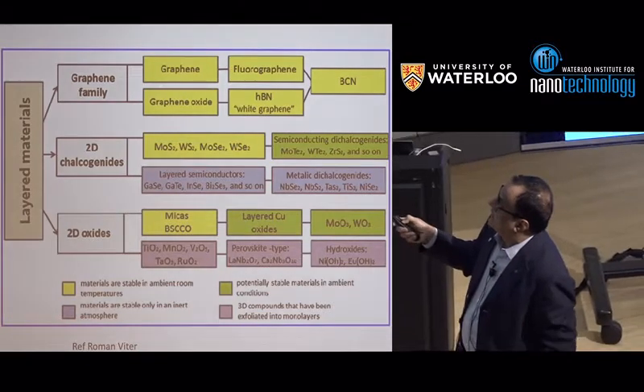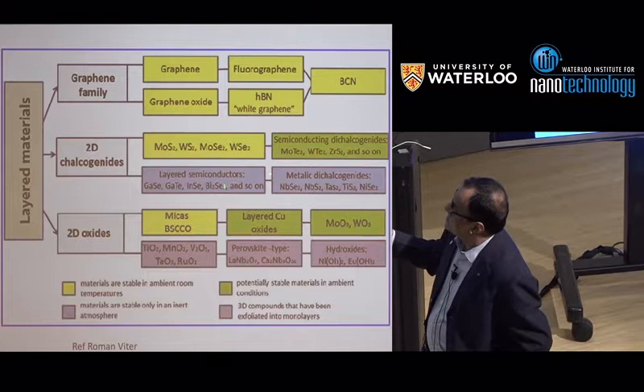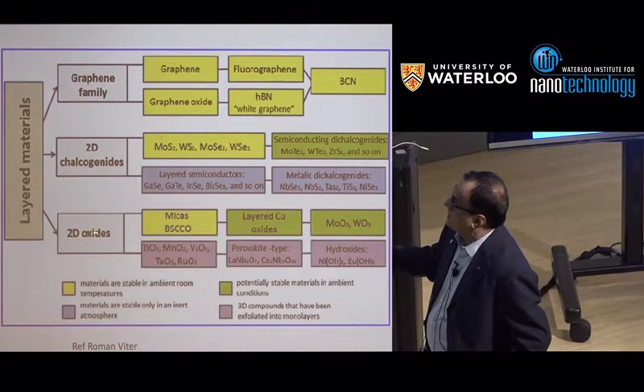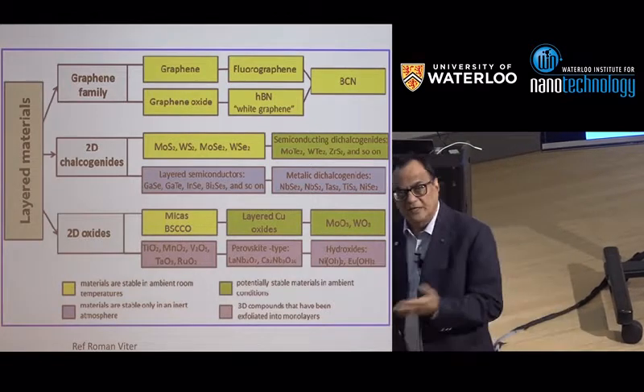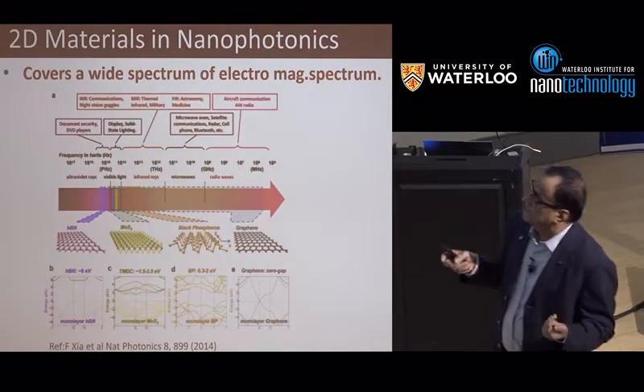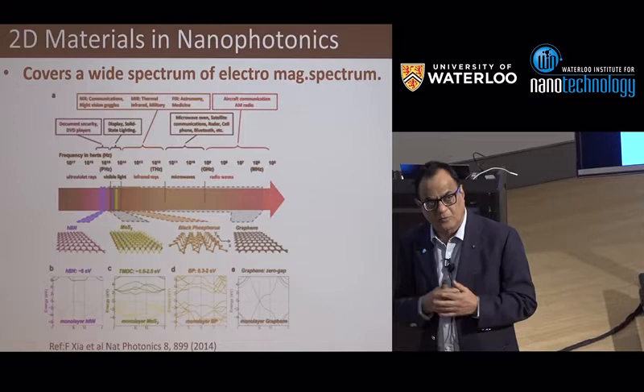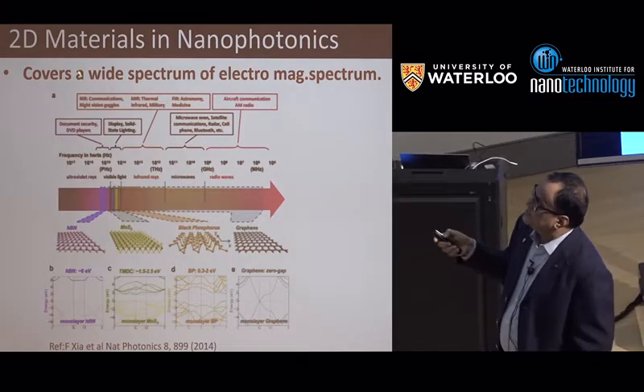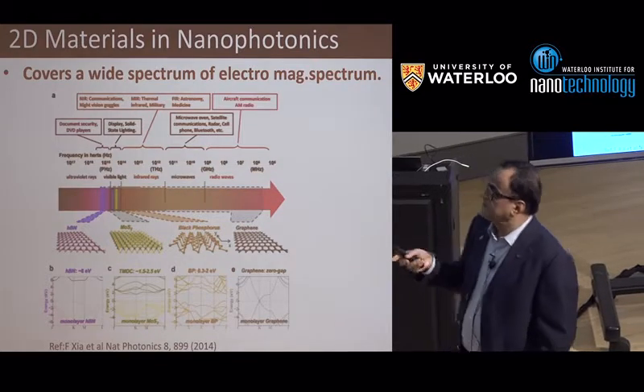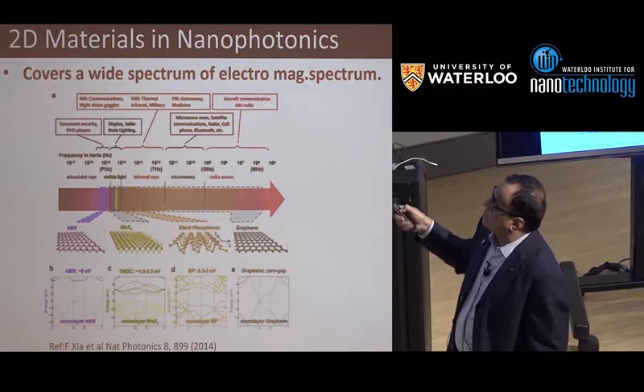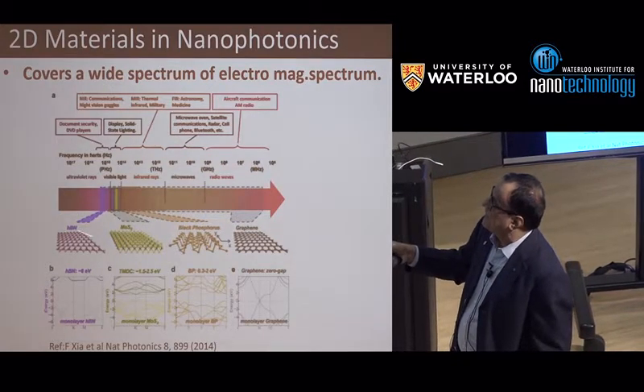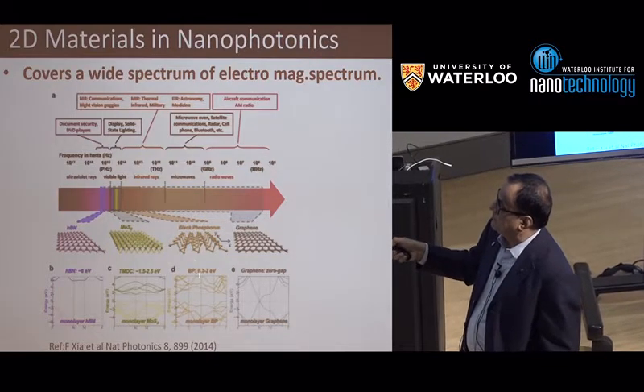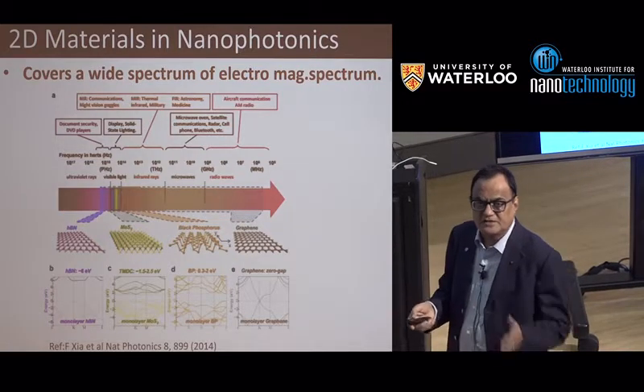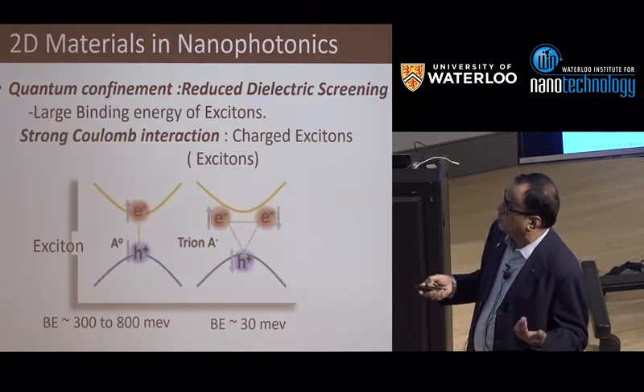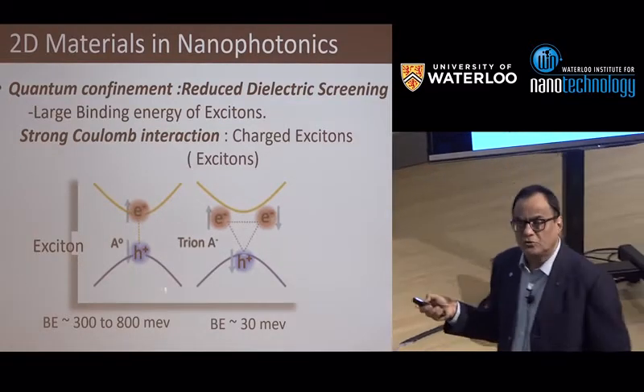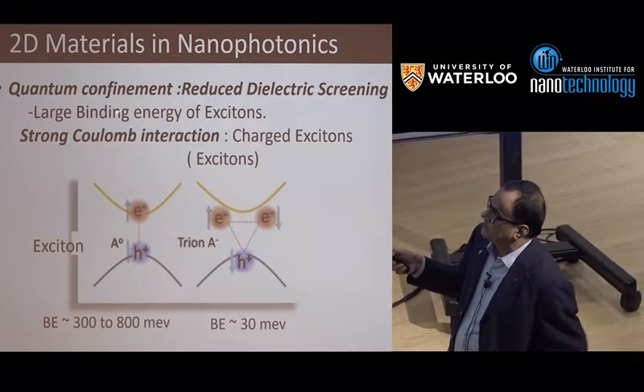I just took these slides: you have the graphene family, you have chalcogenides, you have topological insulators, and you have so many oxides, and these were actually in bulk form, but now you can even make few layers or monolayers. Let me paraphrase for those who are not in photonics for a living: these 2D materials have a huge opportunity, and it's just beginning to be explored, because we can cover a wide spectrum of the electromagnetic spectrum, starting from hBN, with a 6 eV band gap, to graphene, which has 0 band gap, and in between MoS2 and black phosphorus. So huge opportunity, and now with heterostructures in place, you can really play what you want to do. So just to remind you of the things which affect the photonic properties, of course you have quantum confinement in a reduced dimension.